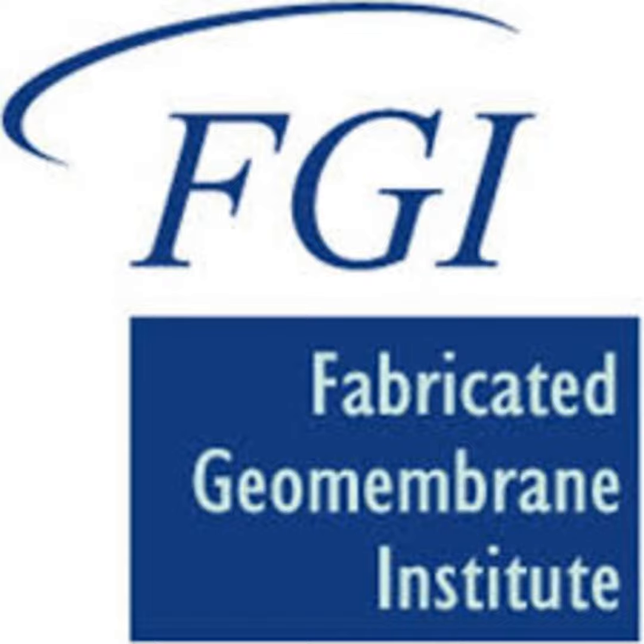At low normal stresses, the critical interface at Kettleman Hills is the nonwoven geotextile geomembrane. And then after a normal stress of 6,000 pounds per square foot, it shifts to the secondary compacted soil, bottom of the secondary geomembrane. And so that's the combination envelope. If there was a GCL involved in that case, you would not use the hydrated bentonite strength or large displacement strength, because that interface would never be the critical interface.